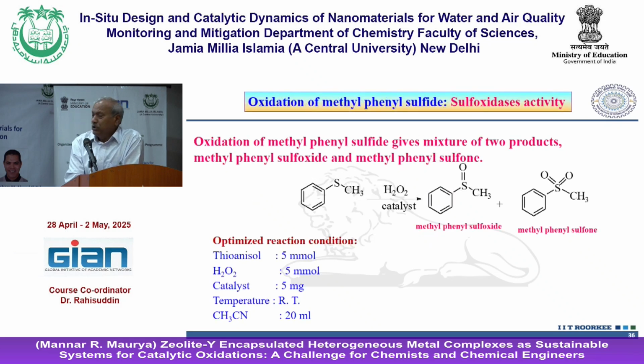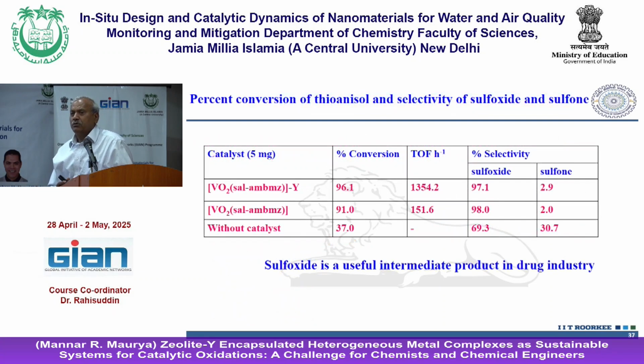Now, the reaction I talked about in the morning. We wanted to see whether this is working with this condition also. So we have taken sulfide, and we are able to convert it even at room temperature. See, the optimized condition is already given here. For 5 millimole of the substrate, H2O2 requires only 5 millimole, with a very small amount of catalyst. Room temperature in acetonitrile, this is giving a very good result. Conversion is more than 90%, giving sulfoxide in very good yield, which is the expected one.